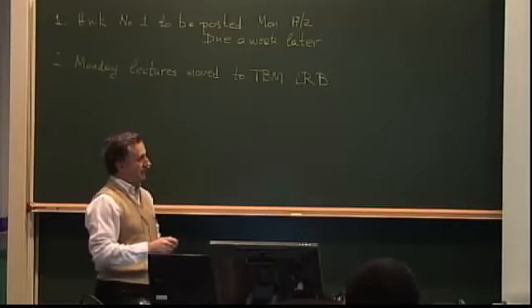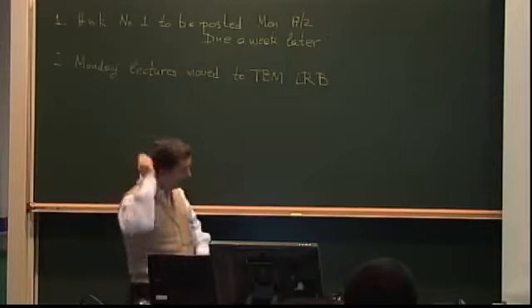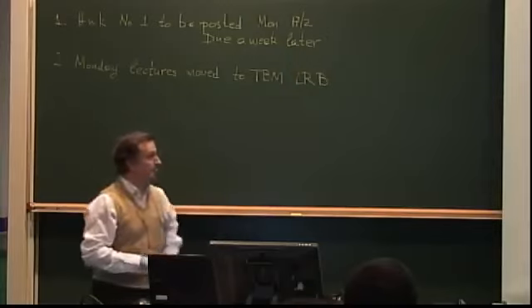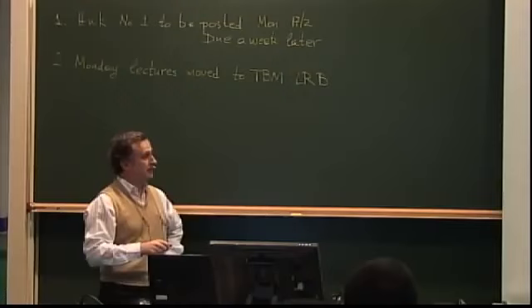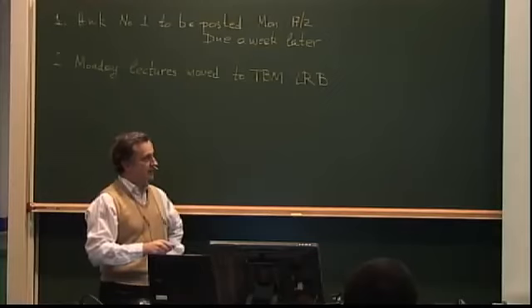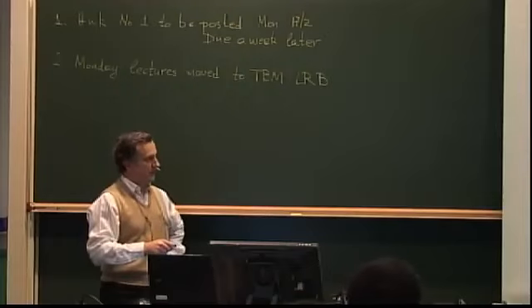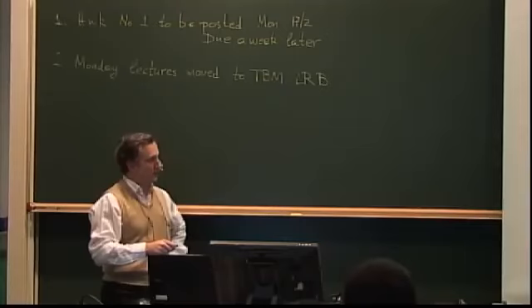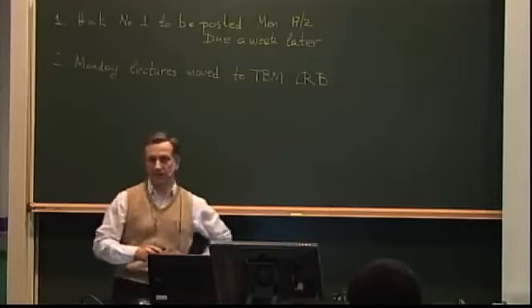And the A's are given as integrals of these Qij's, the Qij's being the stiffnesses. And because through the thickness each of the Qij is constant, I can replace the integration with summation throughout all plies, as long as I calculate correctly the integral dz, which is just the z coordinate at the top of the ply in question, the kth ply, minus the z coordinate at the bottom of that ply.